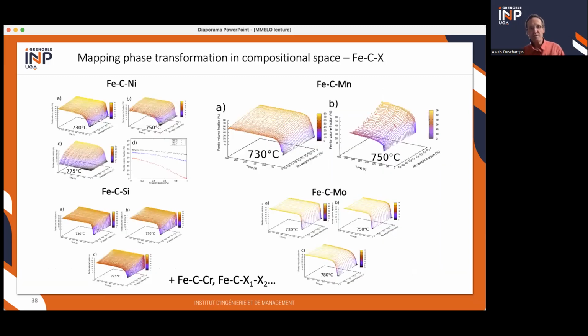So we've been in about 4 days of experiment at DESY in Germany. We were able to do many different cases, 3 temperatures on iron carbon nickel, 2 temperatures on iron carbon manganese. We were looking also at molybdenum, silicon, chromium, and we did even a few quaternary interdiffusion compositions. So these are, I guess, good ways to get a large amount of data that you can fit now with models.